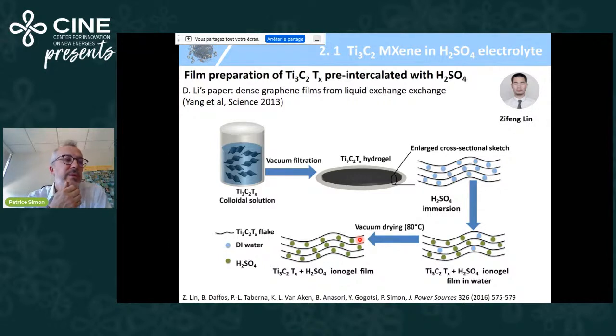And what we did first with Professor Zifeng Lin, who is now a professor at Sichuan University, we tried to design a MXene material, Ti3C2, pre-intercalated with sulfuric acid. Why? To increase the surface area between the electrolyte and the MXene, to maximize the contact between the electrolyte and the MXene. So we started from a colloidal suspension of Ti3C2. We did a filtration. And then, this was more or less a sketch of the electrode after that. You have water molecules in between the MXene layers. We put this in sulfuric acid electrolyte. Little by little, sulfuric acid goes between the layers and water diffuses back into the sulfuric acid electrolyte. Then we dried it.